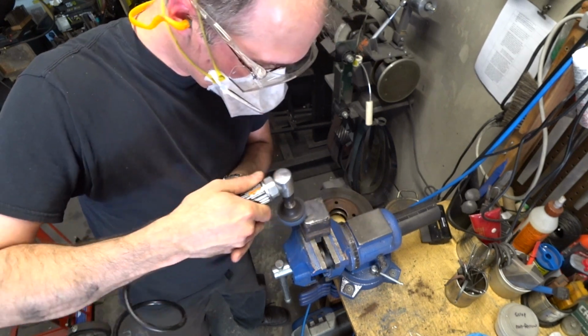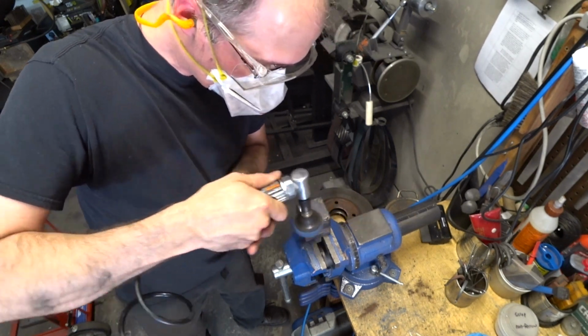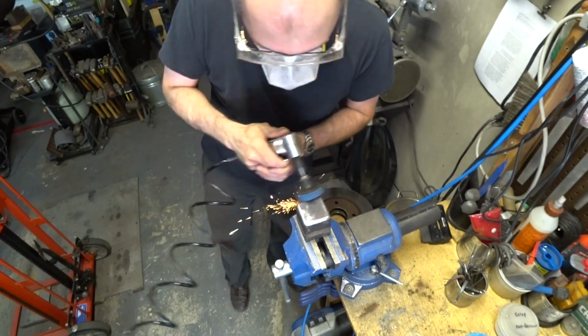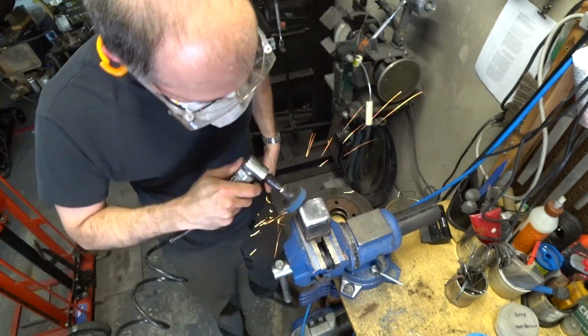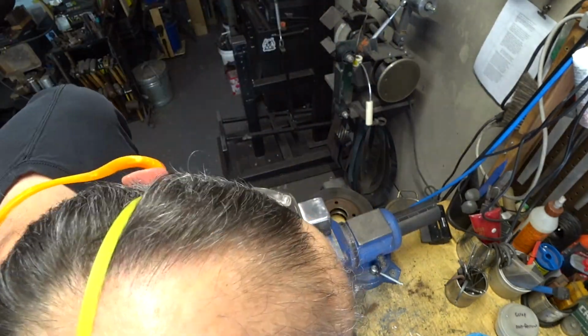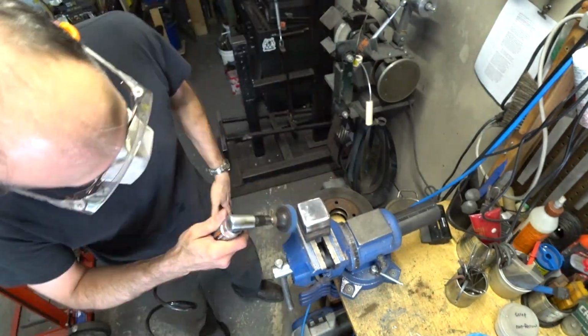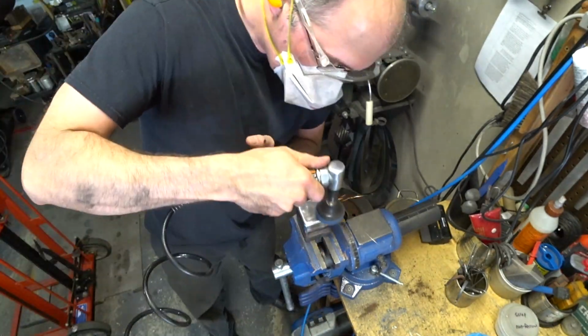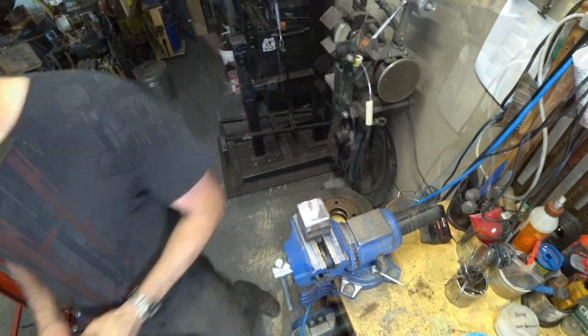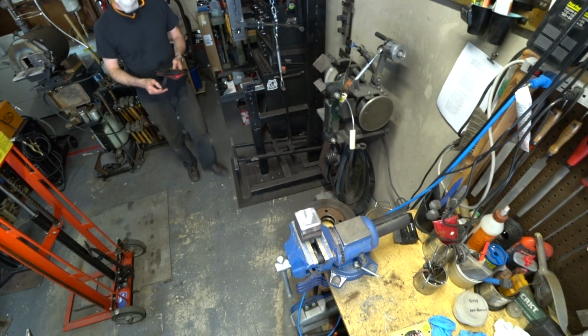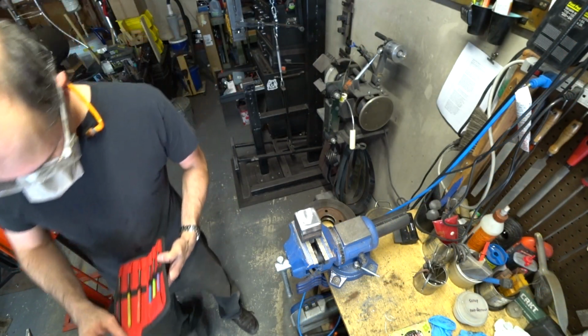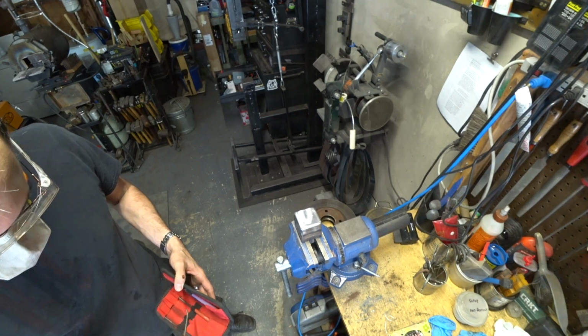It's important that we get down to nice clean metal in order to do the hardness test, but we don't want to grind too deep because the case is not very thick. So all I'm doing here is using a surface conditioning disc on a little air die grinder in order to clean down to the bare metal. And then I'm going to use my hardness testing files to see what kind of a surface hardness we got.